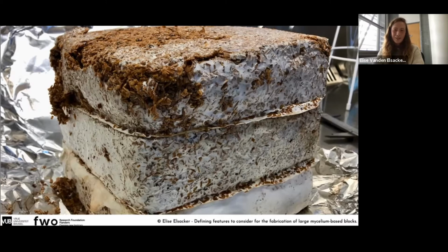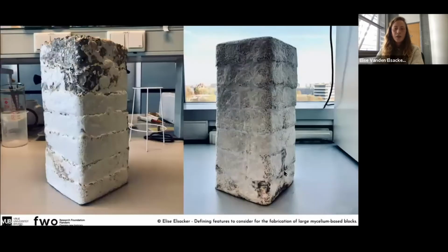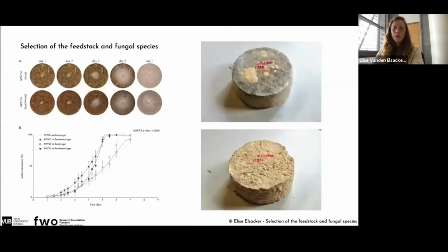But if you compress blocks that are still alive and still wet, the water that has accumulated in the samples will just come out, and the outer skin of the material was damaged. Also during this procedure, it was very clear that the core of the material wasn't really holding the material together, because you can see that fragments of the initial block just broke off. So these results weren't very homogeneous. And then I also tested stacking different blocks on top of each other. These blocks were pre-grown, placed in a mold, and then stacked on top of each other, but without the compression phase. And that was a more successful approach to reach those bigger blocks.